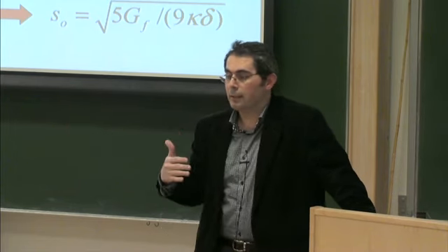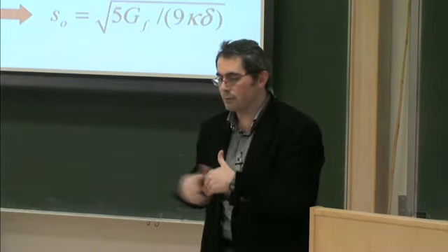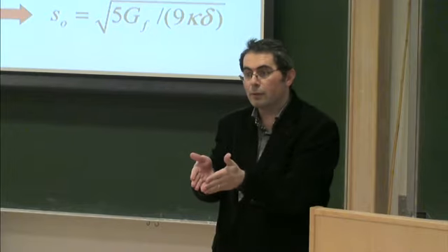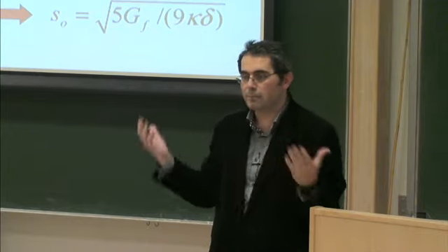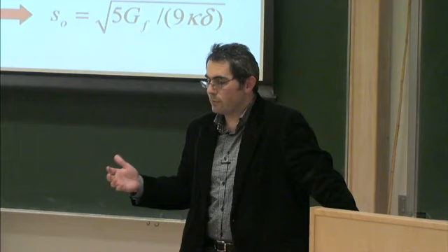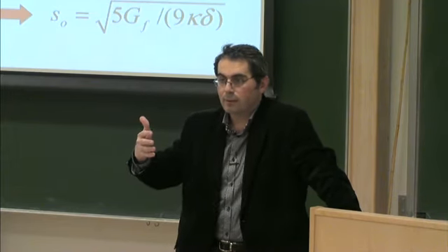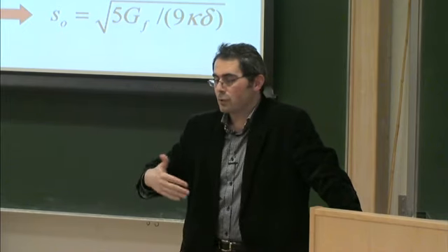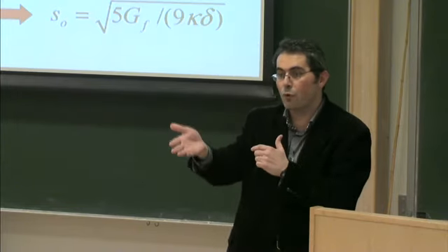But if we converge to 0, then since we are doing these numerical simulations, our discretization should also be very small. So our computational time will be very, very high. So what we need to do is choose a suitable horizon size for ourselves. And then you try different horizon sizes to see that you achieve some type of convergence. And that's what I also showed you for this polycrystalline case.